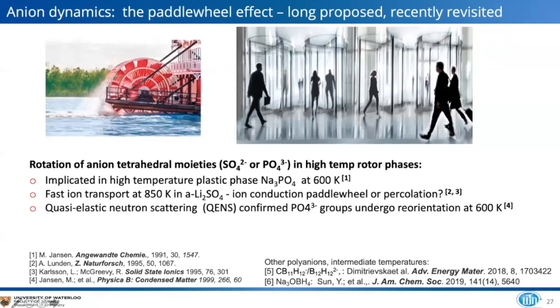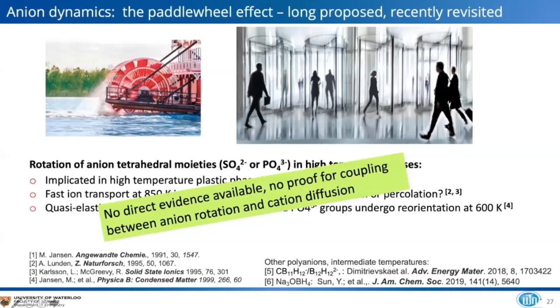These individuals, Martin Jansen in particular, did a lot of work in this, Lunden as well. So they were implicated in high temperature plastic phase of the sodium phosphate at 600 and in lithium sulfate, and quasi-elastic neutron scattering confirmed this reorientational motion at 600 K in work reported by Jansen et al. And more recently, others using AIMD and other complicated, sophisticated techniques, I should say, have looked at other polyanions such as the closoboranes and also the borohydrides, Na3OBH4. So these are fairly recent reports. But it's hard to get direct proof for this coupling between the anion motion and the cation motion. And that's what I'll be talking about a little bit more today.